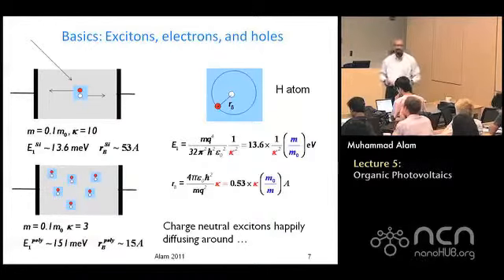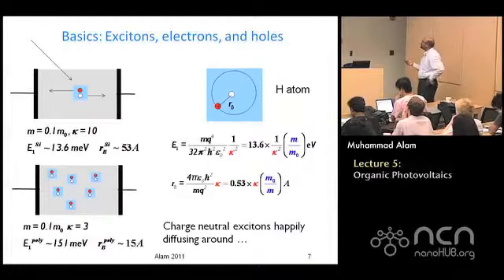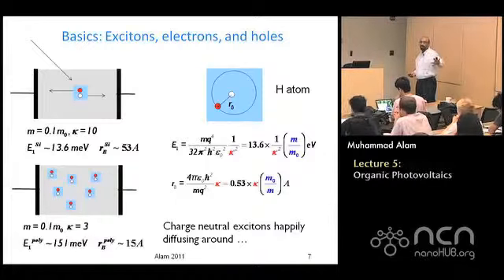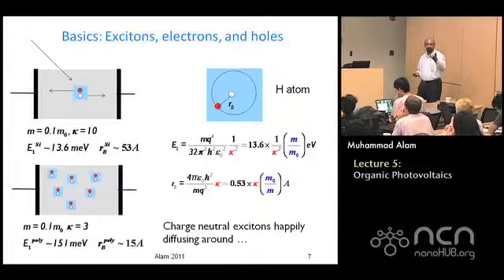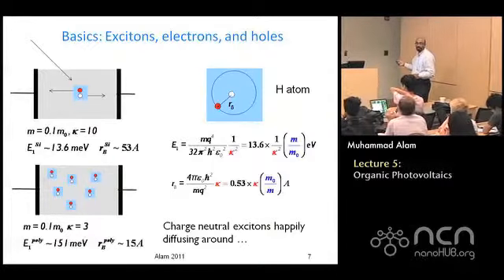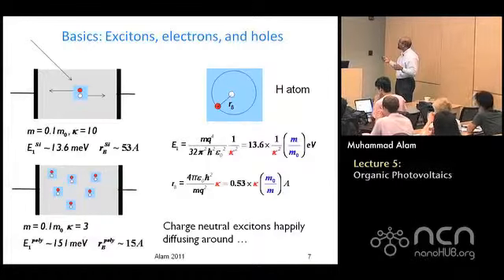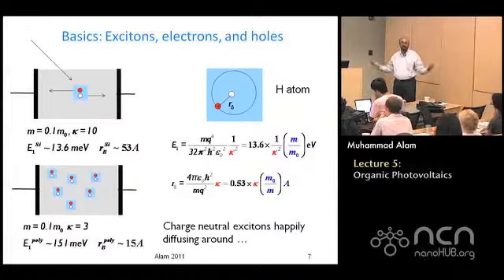Exciton is normal, right? Now, the argument I made was that if you look at the binding energy of how strongly they are bound, in the case of a hydrogen atom, it's in the vacuum, so your relative dielectric constant was 1. So you had 13.6 eV, and if you didn't put an X-ray or something in it, nobody is going anywhere, right? It's very strongly bound. On the other hand, silicon's dielectric constant is 12 or so. Look at this, it goes as kappa squared, so you divide by 144, let's say. Effective mass is 0.1. So instead of 13.6 eV, it is 13.6 milli-electron volt. Now 25 milli-electron volt is kT. So yes, they want to circle each other. If a phonon comes in and kicks one of the electrons, they forget that they were ever excitons. They get out through their respective contacts.